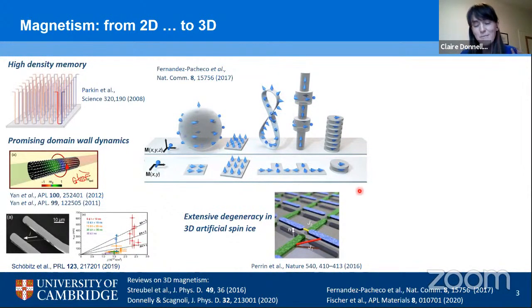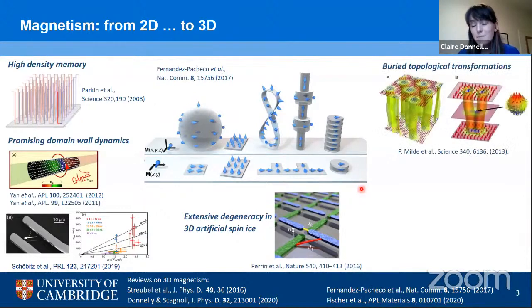Now, three-dimensionality also plays an important role when it comes to topological systems or topological structures. And perhaps the most well-known example of a topological structure these days is the magnetic skyrmion, which you can see in this schematic here. Now, in a magnetic thin film, this magnetic skyrmion could almost be thought of as a 2D structure. However, when we go into larger bulk-like systems, the skyrmions become skyrmion tubes, and there's even the possibility for topological transformations within the bulk that can include singularities of the magnetization.